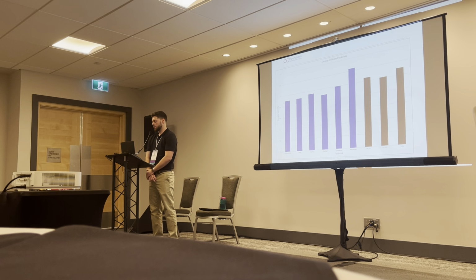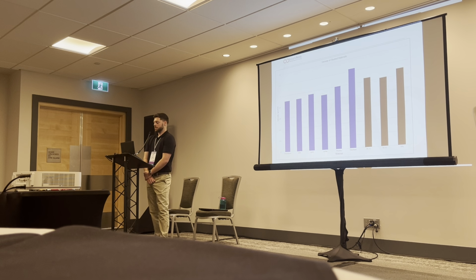So the PA11, all of the densities for the thermoplastics are very, very similar because they're all polymer based. So the very low deviation between the traditional thermoplastics and the 3D printed. However, 3D printed is definitely denser than a lot of the thermoplastics we see. I do want to note that in the 3D printed devices within Boundless, we generally see the 3D printed devices are a little bit lighter for the most part, but there's mixed results for that. But keeping in mind that most of those weight reductions that we could possibly see in a 3D printed device is because of design, not necessarily the material properties of that specific material.